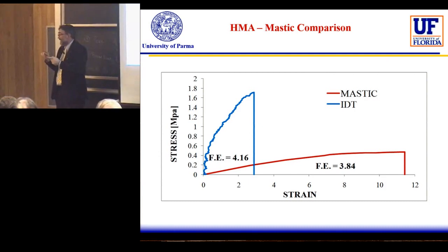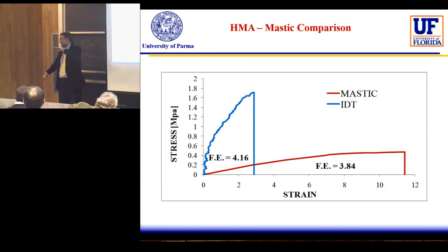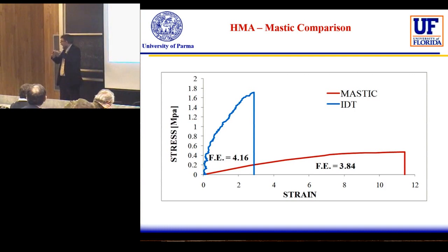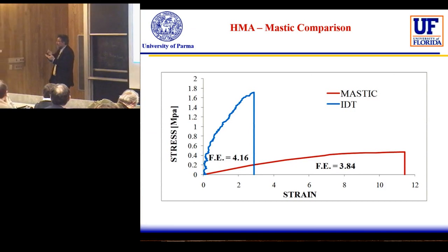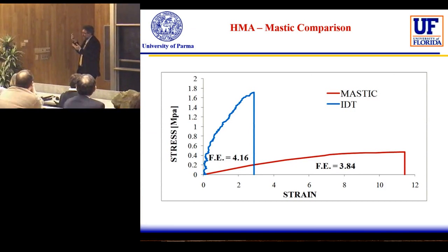So it probably is an effect of the size too, because we define filler as below 0.075. But even there, we can have different size distributions. So probably it is a size effect. It is the size, the surface, and how much chemically and physically active it is. This is a combination of the interactions. The fact is that because the filler is very fine, the interaction is higher with the components of the bitumen. So we can have different changes. It's a real change in the physical behavior.